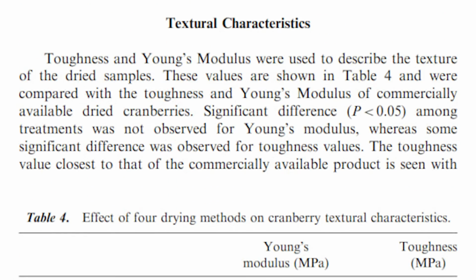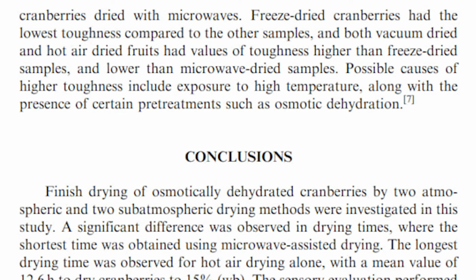Textural characteristics. Toughness and Young's modulus were used to describe the texture of dried samples. These values are shown in Table 4 and were compared with the toughness and Young's modulus of commercially available dried cranberries. Significant differences among treatments were not observed for Young's modulus, whereas some significant differences were observed for toughness values. The toughness value closest to that of commercially available product is seen with cranberries dried with microwaves.